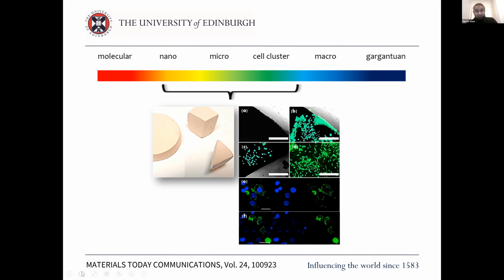And as you can see there on the left, we managed to make these kinds of architectures. You could, of course, subtractively manufacture those as well. But what we did is we accelerated the rate of solid state diffusion between the frustules so that they would actually merge into each other, otherwise known as sintering, so high temperature, high pressure. And then we grew our cells on the surfaces of these three-dimensional architectures.